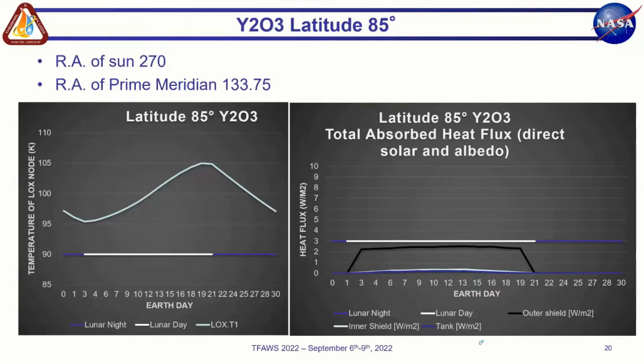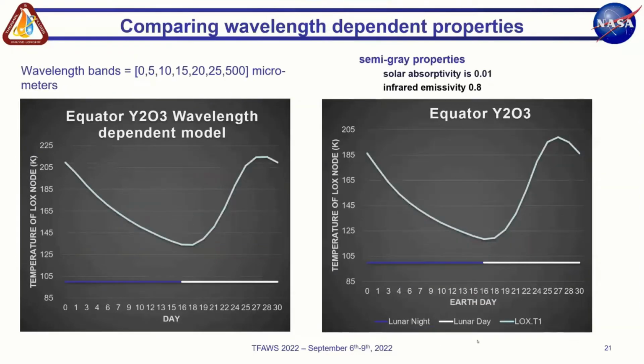So let's go to the next slide then. Comparing, this is kind of interesting. If you do a wavelength dependent model, you're probably going to get more accurate results. Depending on the complexity of your model, it could take a really long time to run. So you have to be careful with that, because you have to run RadCAD for every wavelength band, and that's why it takes so much longer. But you can get more accurate results. You can see here it makes a bit of a difference, probably because I'm just assuming IR is 0.8 there, but now it's actually integrating over that part where it's increasing to 0.8.